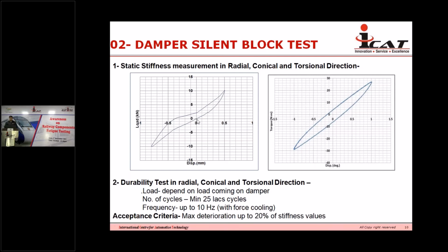In the radial graph, we apply plus minus 1 mm displacement, and we check how much load is coming, and then between plus minus 1 mm of deflection, we check how much stiffness is there. So we find a value in kilonewton per mm or Newton per mm in radial stiffness. And similarly in conical and torsional stiffness, we find out how much torque per degree is the stiffness, like Newton meter per degree.